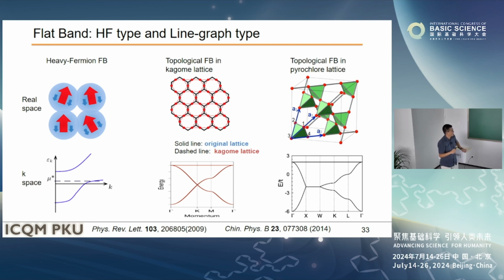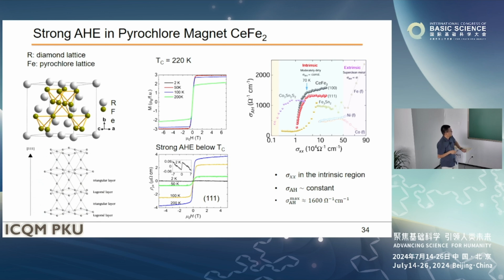So this is a topological flat band, right? For the pyrochlore lattice, it is a line graph of a diamond lattice. We also see a flat band, and there's a parabolic band touching at the gamma point. This touching is a topological touching. We also see some interesting behavior. Okay, so motivated by this pyrochlore lattice, we also try to grow some compounds and see what's going on. One idea is to grow these rare earth iron 2 or manganese 2 compounds, which have the Laves phase structure. Here the rare earth forms a diamond lattice, and iron forms a pyrochlore lattice. So basically we try to see what's going on for the iron pyrochlore lattice.